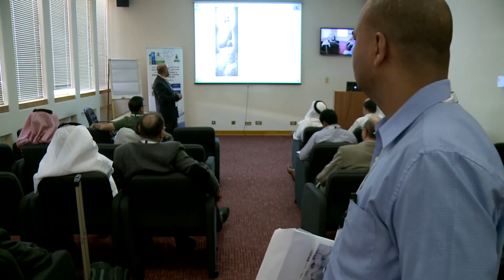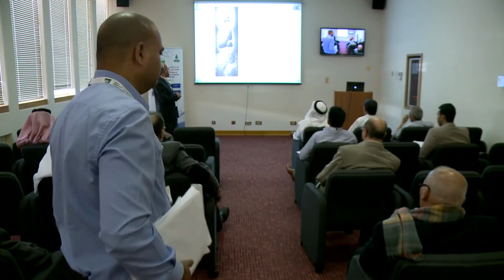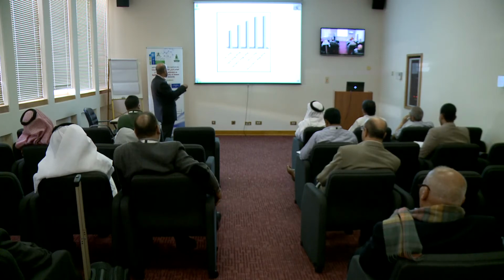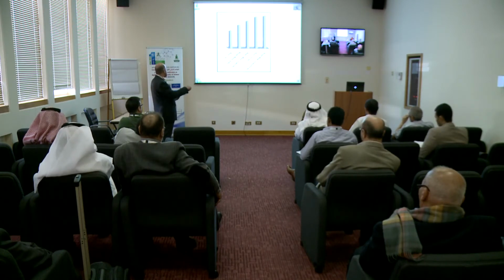This is the XRD for the iron nanoparticles itself. It has different oxide forms, iron 2 and iron 3. And when we support them on the graphene, we have just zero valence iron. Iron exists in the elemental form. We studied the efficiency for the degradation of nitrate using the different nanoparticles that we have. We found that the iron coated with copper supported on carbon nanotubes has the highest efficiency compared with just iron nanoparticles itself. Here we use 5 milligram, and here it's 5 milligram, and the efficiency when we use the iron coated particles supported on carbon nanotubes is almost 100% more compared with the original one.